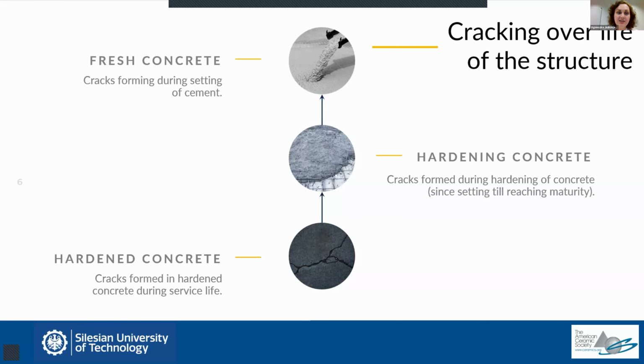As for this first type, cracks in fresh concrete usually do not have that much structural meaning. The cracks which happen during hardening are already very dangerous, because if they appear, and they usually do, it means that when the structure is put into operation, it is not in a zero stress state as is usually assumed, but it is already in a way pre-stressed and pre-damaged.